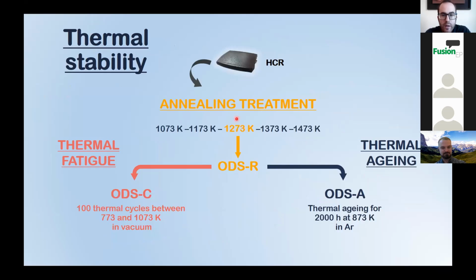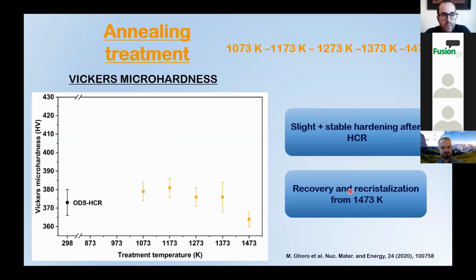With an annealing study, we selected 1273 Kelvin as the optimal annealing temperature. From this point, two independent thermal treatments were applied to the ODS steel. On one hand, a thermal cycling treatment, and on the other, a long-term aging thermal treatment. We obtained the first results on Vickers microhardness focused on the annealing treatment. The ODS steel experienced a slight and stable hardening along the different annealing temperatures, but not at the highest temperature. This could be associated with mechanisms of microstructure recovery and recrystallization.